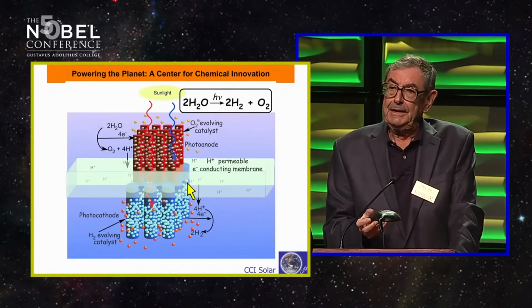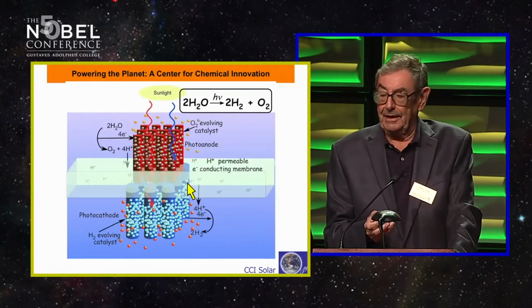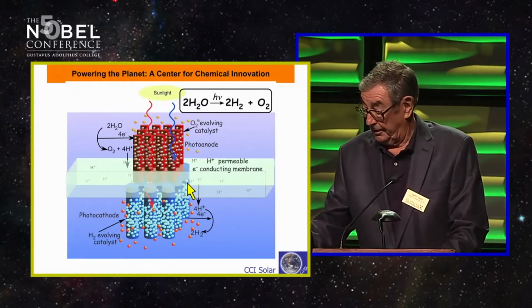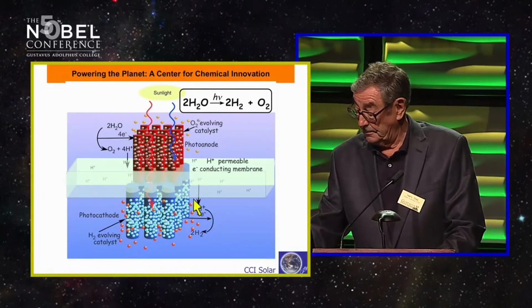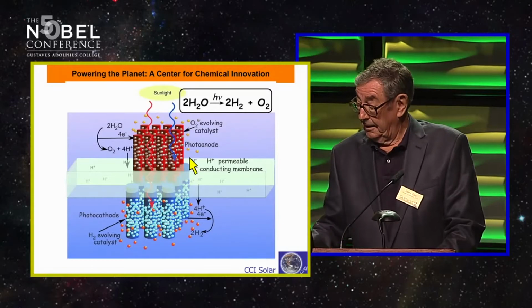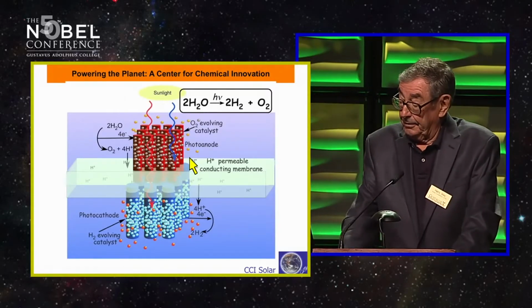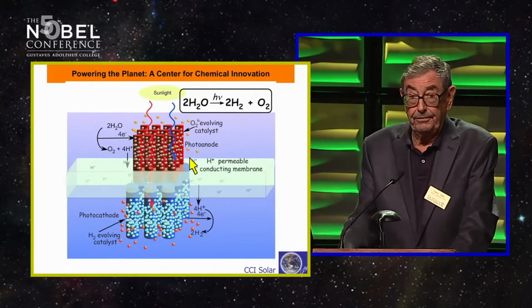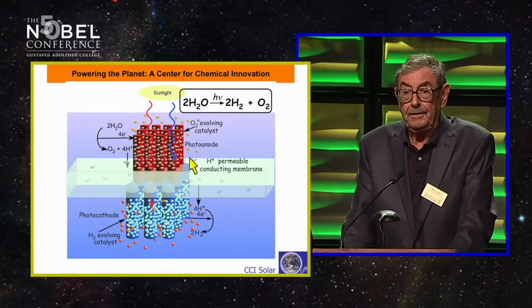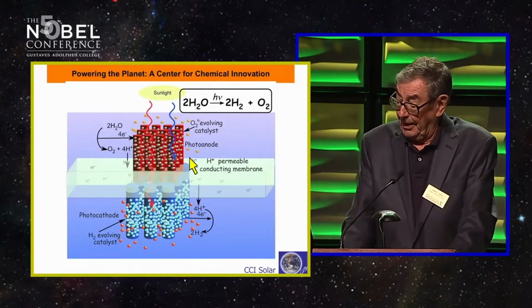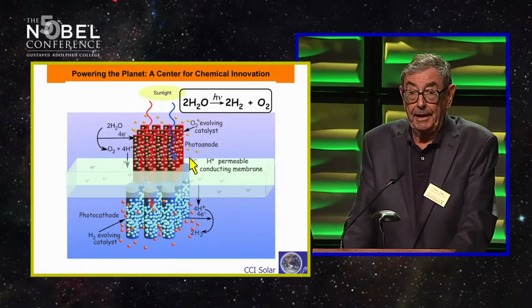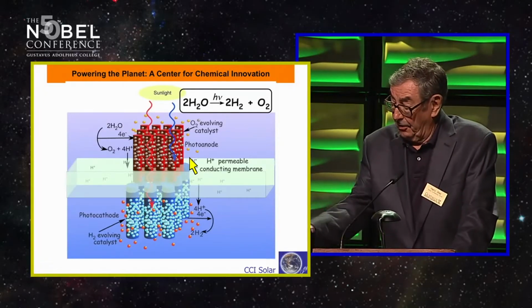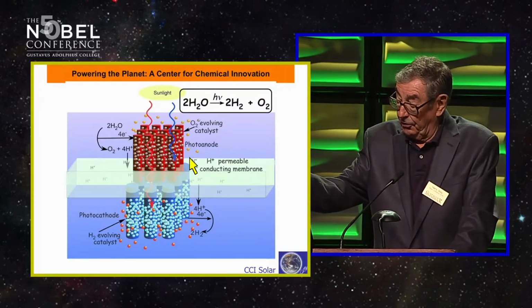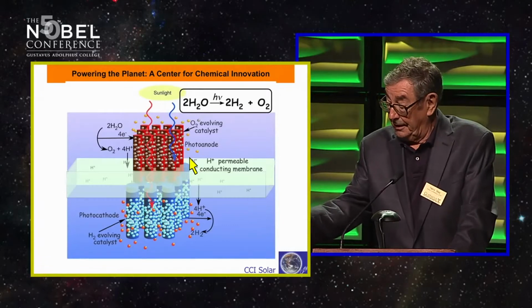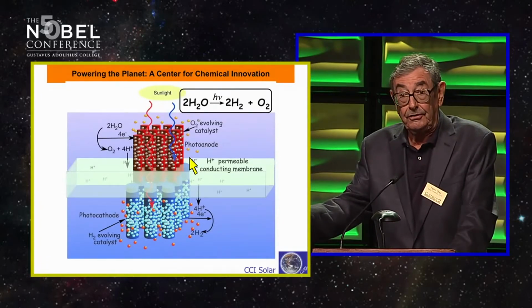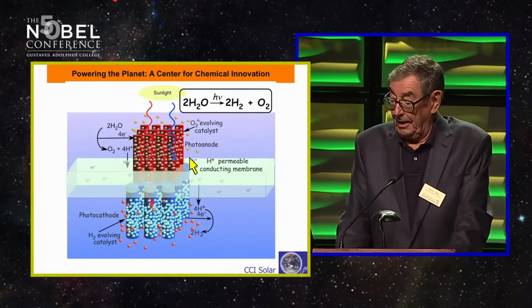They're disordered. And so they tend to recombine to make heat, and we've got to get these electrons and holes to the surfaces. For example, in the photoanode up here, we've got to get the holes to the surface after blue light excitation. And so we'll build a photoanode up here out of some kind of substance like tungsten oxide, to give you one example, and make it into these micro rods that are about 300 microns long. They're long and skinny because we need to absorb all the light going down the long direction, but we need to get the holes to the surface, so it's skinny in this direction because we can't move them very far after excitation.